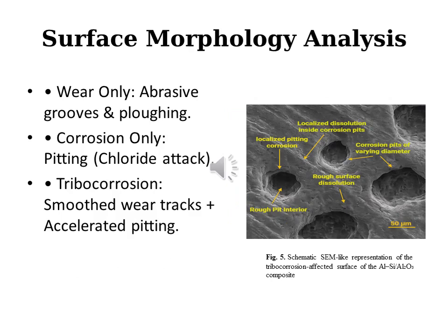In slide 9, surface morphology analysis. Figure 5 illustrates the surface morphology under wear only. We see abrasive grooves. Under corrosion only, we see chloride-induced pitting. However, under tribocorrosion, we observe a combination of smooth wear tracks and accelerated pitting, confirming the interaction between the two mechanisms.